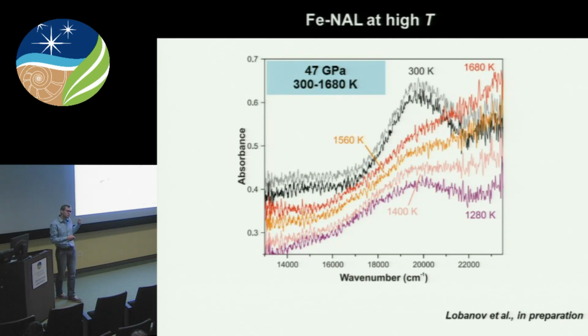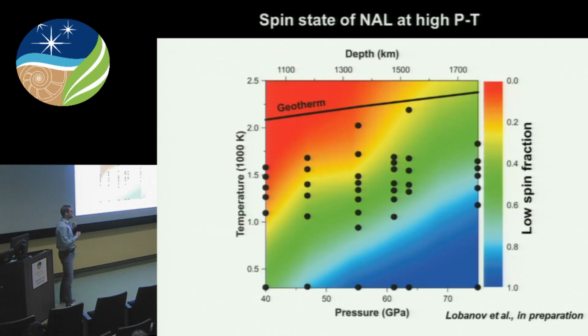So we can now do high temperature measurements, and here the gray and black spectra show you the before and after heating spectra of NAL at 47 GPa. And you can see that you can use the area underneath this low spin Fe3+ band to quantify the amount of the low spin fraction that you have at high temperature. So as you heat your sample, the area underneath this band continuously diminishes, which, in my opinion, records information on the amount of low spin fraction in the hot sample. So we can do that at several different pressures to construct spin state diagrams.